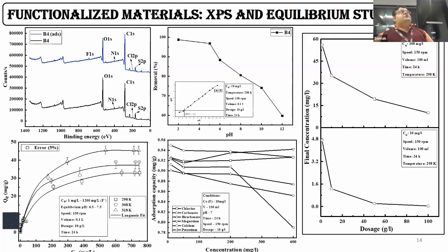But compared to higher concentration, the saturation effect was not seen because the concentration of fluoride was in abundance, and thereby you need to increase the dosage concentration to something like 100 or even more, for 100 gram per liter or 150 gram per liter of the adsorbents.